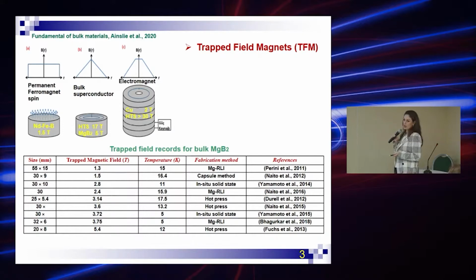Nowadays, bulk superconducting applications may be in two main categories. Firstly, trapped field magnets, and secondly, magnetic levitation devices. And it is quite obvious that larger dimensions and different shapes of materials are more and more desirable. When a bulk superconductor is exposed to an applied field below its TC, it acts as a strong diamagnet, and concentric supercurrents are induced within the bulk sample during the magnetization process. When the external field is reduced to zero, the supercurrents persist, and the resulting magnetic field, called the trapped magnetic field, has a magnitude much greater than that of iron-based conventional permanent magnets.